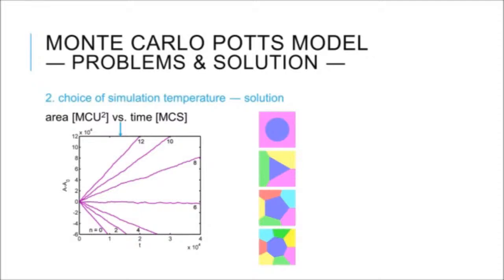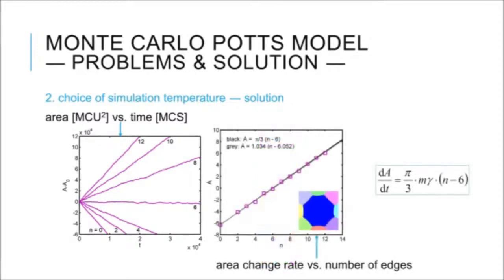It's always a linear function of time. We can plot the area change rate against the number of edges, and we can see that basically a linear least squares fit is identical to the prediction by von Neumann and Mullins. So we found for this very implementation just the perfect simulation temperature.